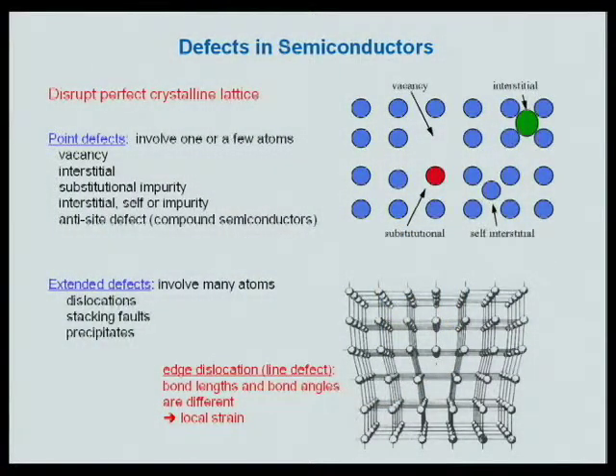Okay, what is a defect in a semiconductor? Well, a defect is basically anything that disrupts this perfect crystalline lattice. And we can have point defects, which only really involve one lattice site and maybe the immediate atoms close to that lattice site. We could have a missing atom, which is called a vacancy. We can have an extra atom that's just stuck in there between the regular lattice sites. It would be an interstitial. And that could be an impurity interstitial, or it could be just an extra silicon atom in the case of silicon. Or we can have a substitutional impurity where one of the lattice atoms is replaced by an impurity.